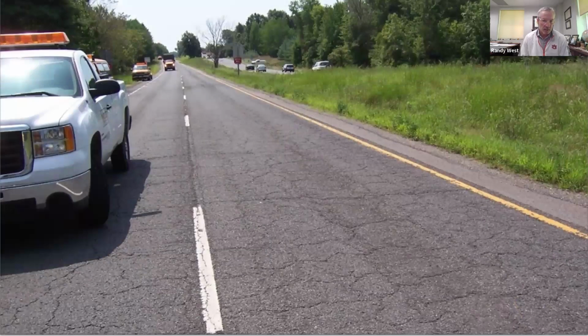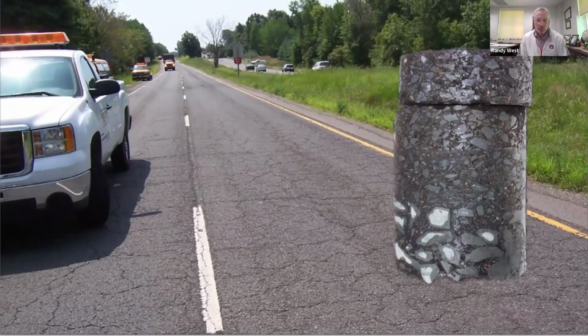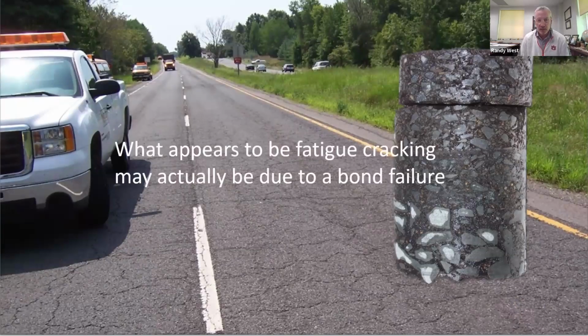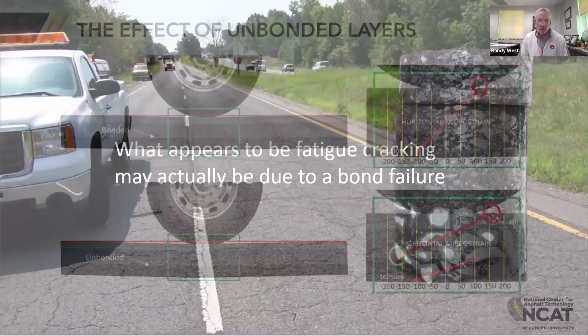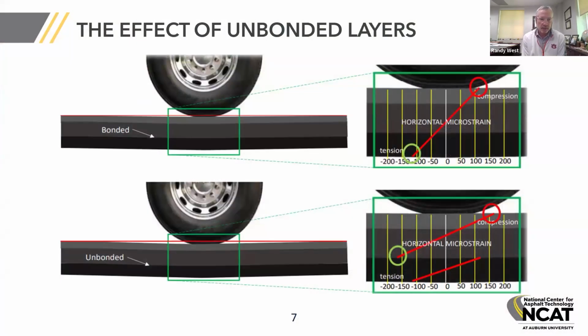You see this pavement here, you may think, oh, that's top-down cracking or bottom-up cracking. But if you take cores from a lot of these kinds of pavements, you'll see there's a debonded layer there, and that is contributing to the cracking that you're seeing on a lot of the pavements we have. So what appears to be fatigue cracking may actually be due to a bond failure. So let me explain that a little bit.